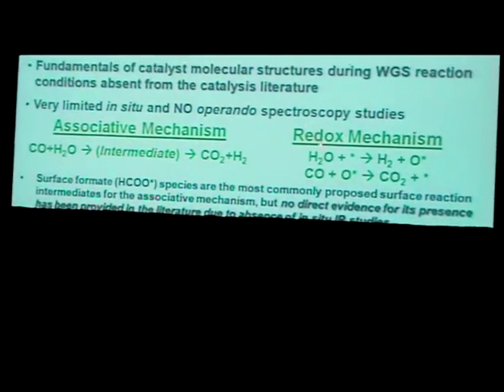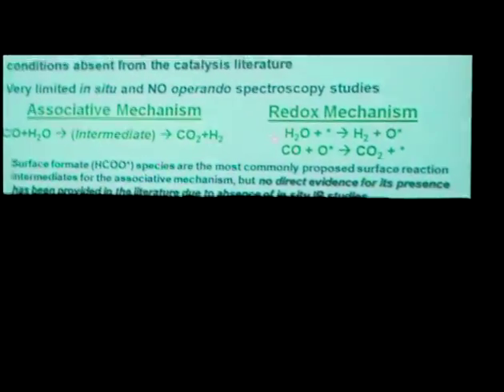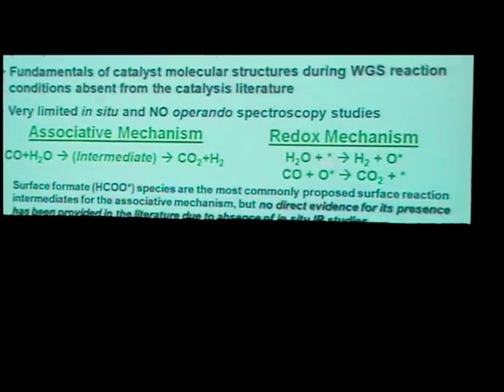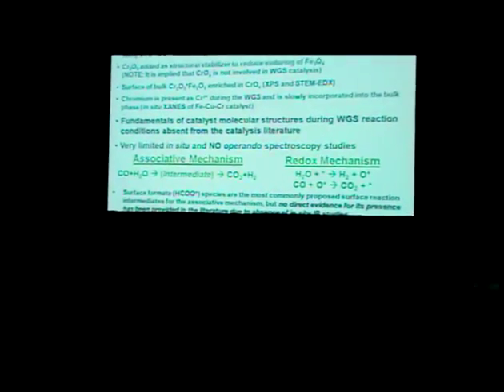The second mechanism is one of a redox, where the water reacts with a vacant site in the catalyst, giving up the oxygen and generating hydrogen. And in the second step, the CO picks up the oxygen and makes CO2, regenerating the empty site. So I want to first look at what the catalyst looks like during the reaction, and what we can say from the information we have about this mechanism.